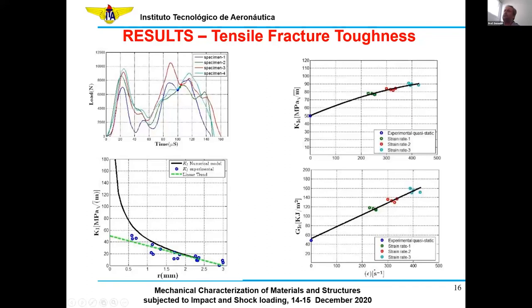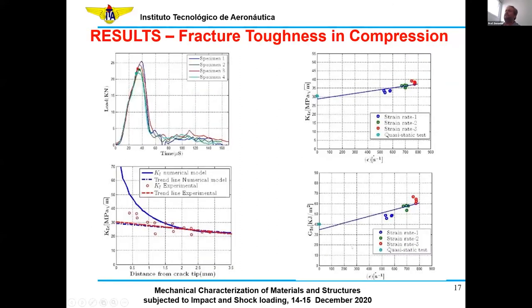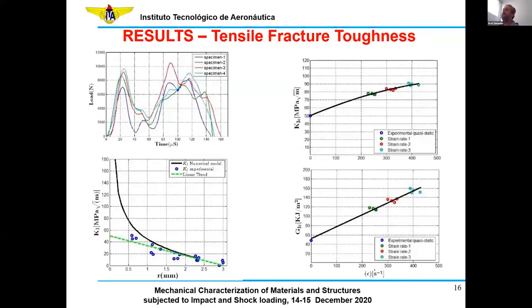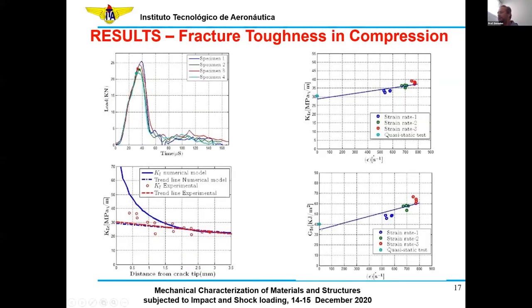Here I show some results showing how the stress intensity factor varies with the strain rates. We can see here that it is very sensitive to the strain rate, where we have an increase or enhancement on the stress intensity factor, as well as on the intralaminar fracture toughness, with the strain rates. The same also applies for the intralaminar fracture toughness in compression, where we have also an enhancement on the stress intensity factor with the strain rates.